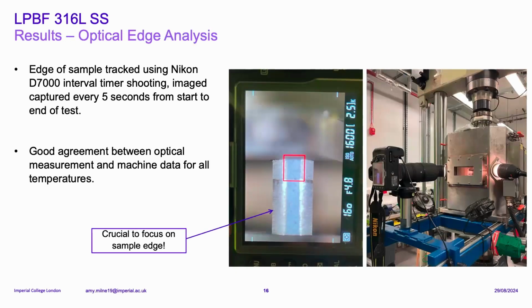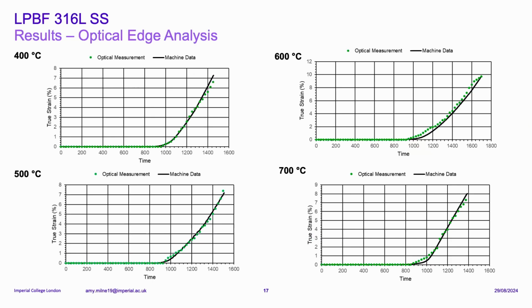So going back to the optical analysis that I was performing at the same time. The edge of the sample was tracked using the Nikon D7000 interval timer shooting setting every 5 seconds from the start to the end of the test, which lasted approximately 40 minutes for each sample. I did find good agreement between the optical results and the machine displacements. This is really useful for the future because it's not always possible to use things like capacitance gauges inside tests. So it's good to know that the optical method can provide a way of monitoring the sample in real time and getting those axial and radial displacement results externally from the furnace.